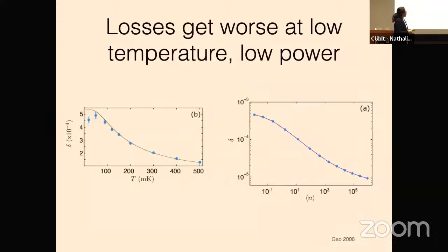The other thing that people know is that the losses get a lot worse at low temperature and low microwave power. This is a plot of the loss tangent as a function of temperature and as a function of microwave power from Jiansong Gao's thesis. You can see that the loss goes down with temperature and also goes down with microwave power. And this is very weird, because normally if I just give you a chunk of something and ask you to characterize its losses, it should just be linear. But here, you increase the microwave power and you get lower losses, so you have something that saturates. And this is why people talk about two-level system loss in these kinds of systems.